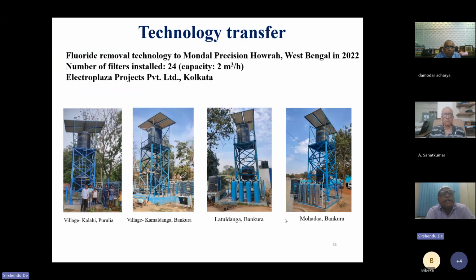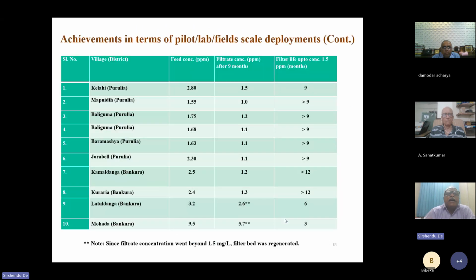So this technology was transferred again to companies, and they came up with 24. By now there are 34 filters that have been deployed in different places of Purulia, Bankura district, and now this chart is very important. This gives a filter life at different locations, and if you look into this, based on the feed concentration of the fluoride, and we have just charged around 80 kg of the material in 2 columns, we have seen that depending on the feed concentration of the fluoride, the filter life will be varying from 9 months to more than 12 months. So these filters are designed for 12 months, and then after 1 year, the media has to be replaced.